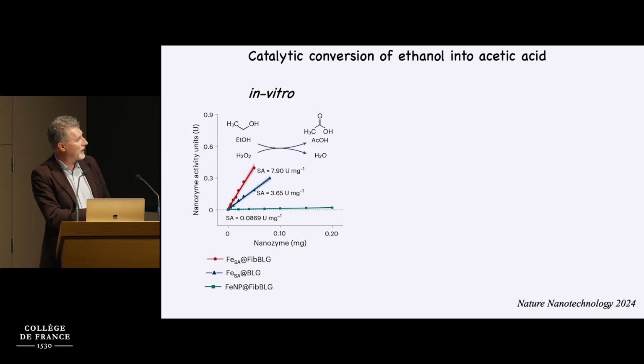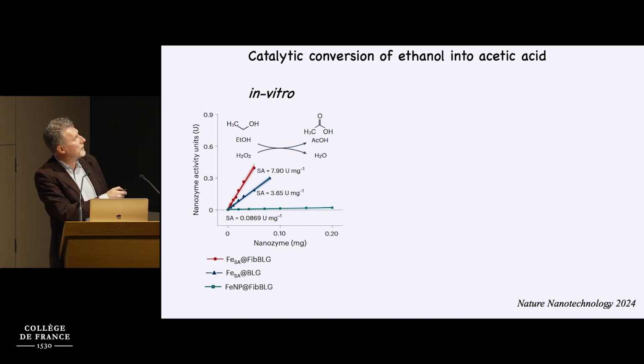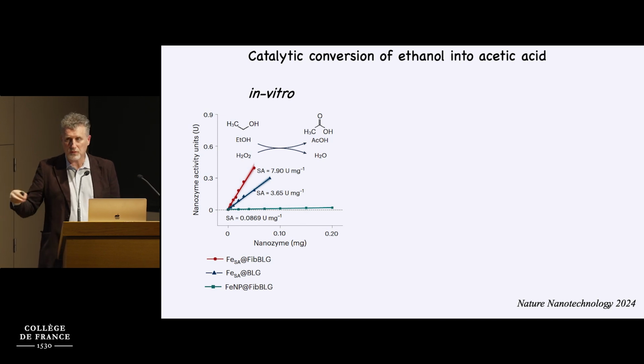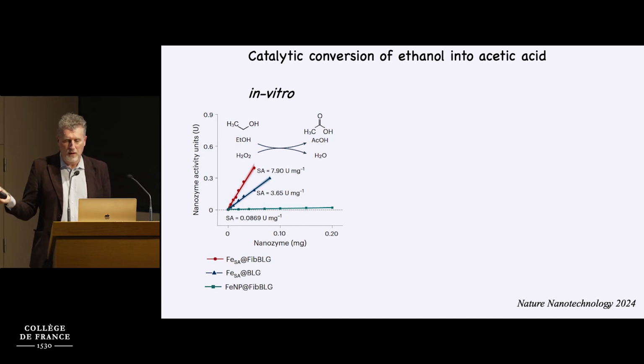Nanoparticles have lost all the activity. You see that the fibers have an enzyme activity which is about twice as much as the monomer. And what we're doing here, we're converting ethanol into acetic acid without transiting through acetaldehyde.